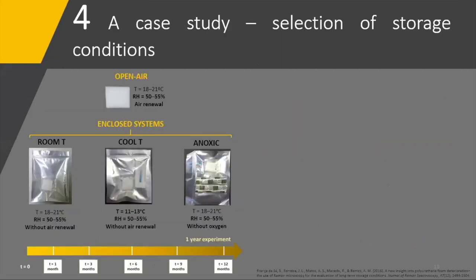And here is a case study from my PhD, in which several storage conditions have been assessed for the preservation of polyurethane foams in the dark. For this assessment, two main conditions were defined: open air, and sealed enclosures made of barrier film bags. And among the enclosed, room temperature, cold temperature, and anoxic were tested. This experiment lasted for 1 year, and the samples were collected after 1, 3, 6, 9, and 12 months, and analyzed by multi-analytical techniques.